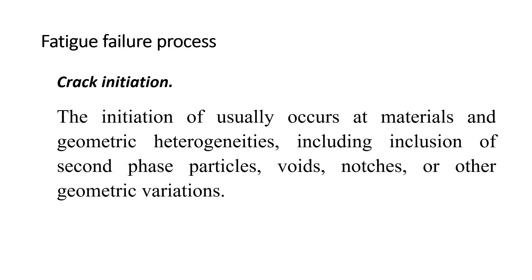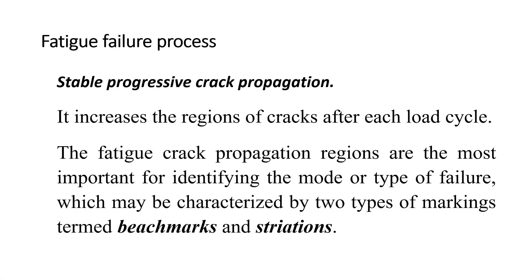Crack initiation usually occurs at material and geometric heterogeneities, including inclusions of second-phase particles, voids, notches, or other geometric variations. Stable progressive crack propagation increases the region of cracks after each load cycle. The fatigue crack propagation region is most important for identifying the type of failure, which may be characterized by two types of markings termed beach marks and striations.